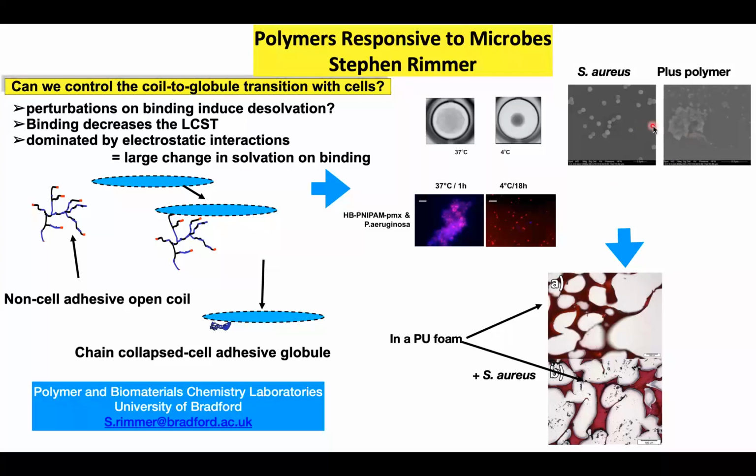Here, this is another polymer. This time it's a gram-positive selective polymer, and in the electron microscope you can see the Staphylococcus aureus in the absence of the polymer, and then aggregated after we've added that selective material. These are being used by us as diagnostic devices for selective detection of pathogens, but also as sampling systems. And clearly we can take these aggregates and use them to manipulate the bacteria.